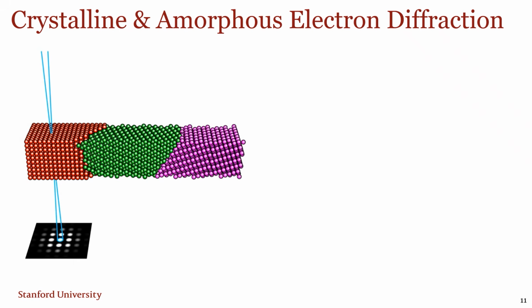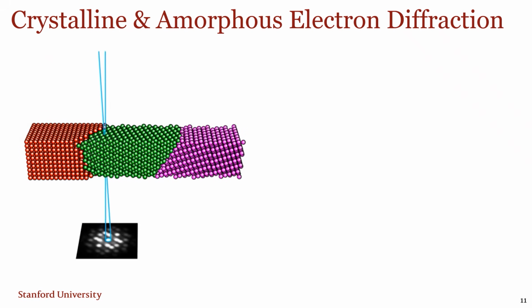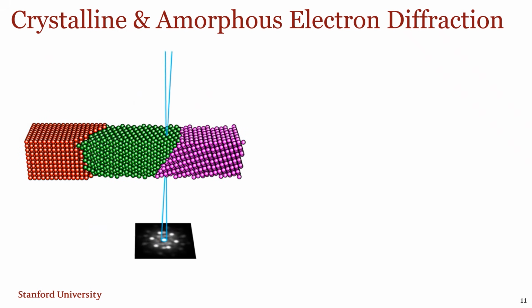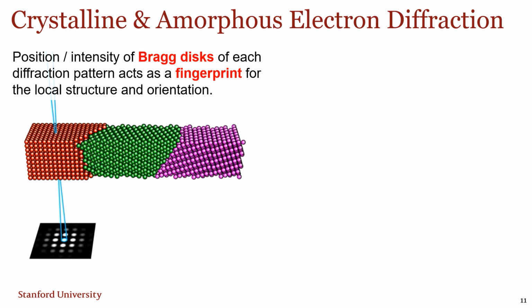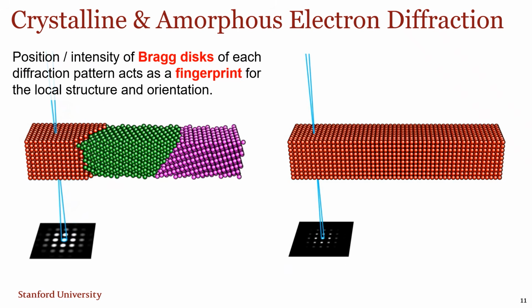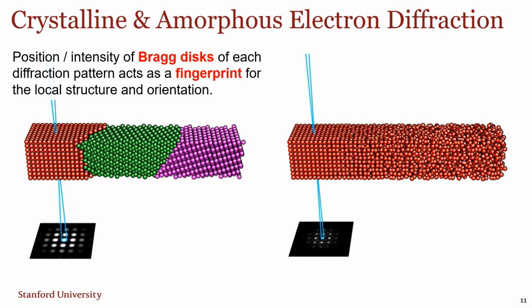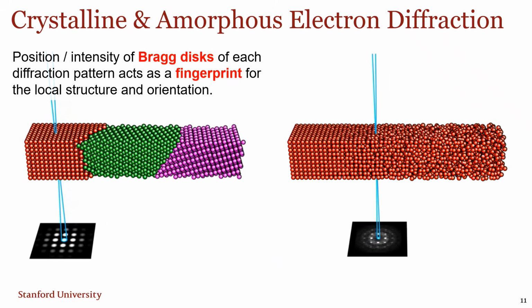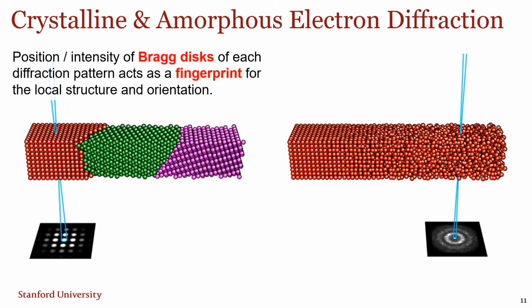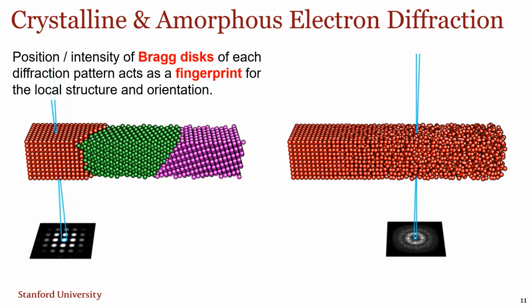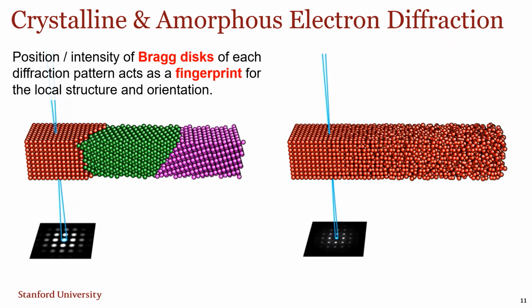Okay, so just to show you an example of this, if we had a crystalline sample and we were to scan the probe across the surface, you can imagine that these diffraction patterns are fingerprints of the local phase and orientation. And it doesn't just work for crystalline materials. If I take a toy model and I randomly move all the atoms in this sort of linear path and scan the beam through, what you'll see is the two-dimensional grid of peaks, Bragg peaks as we call them, is replaced by these characteristic amorphous halos.